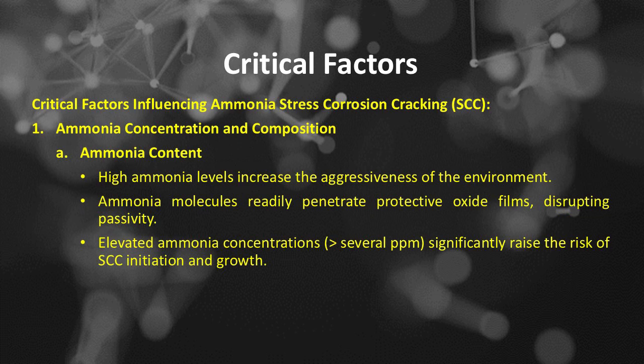Critical factors influencing ammonia stress corrosion cracking, or ammonia SCC, include, number 1, ammonia concentration and composition, which includes, number A, ammonia content. High ammonia levels increase the aggressiveness of the environment. Ammonia molecules readily penetrate protective oxide films, disrupting passivity. Elevated ammonia concentrations, greater than several ppm, significantly raise the risk of SCC initiation and growth.